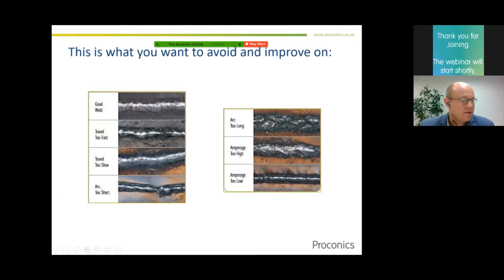So there's a lot of essential variables that you have to take into consideration. This is just to mention a few of them. So if your amperage is too low, your amperage is too high, your arc is too long, your arc is too short, and your travel speed is too slow, travel speed is too fast, this will all affect a bad weld.